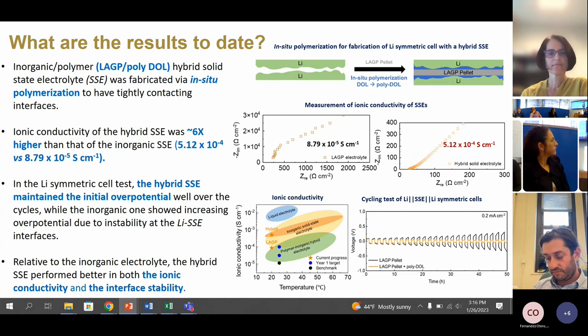So for the results here, a few things I will talk about. We've seen high ionic conductivity, which is about 6x higher than some of the other solid state electrolytes, which was nice. The in-situ polymerization process, as I mentioned, you can see here the interfacial gaps between these lithium metals. And when you have this solid ceramic, you could see where the gaps would occur. In this case now, it essentially fills in the gap, increasing the interfacial stability, which allows for high ionic conductivity and thus overall higher performance.